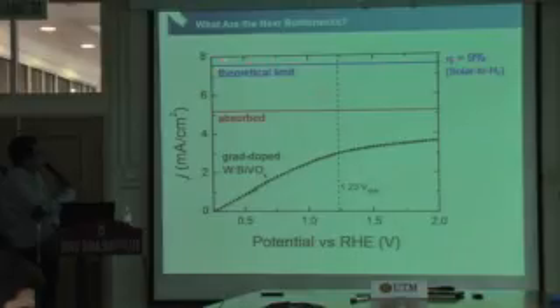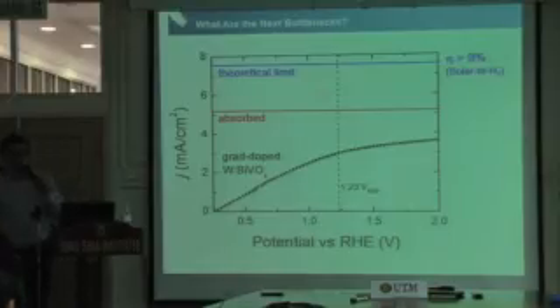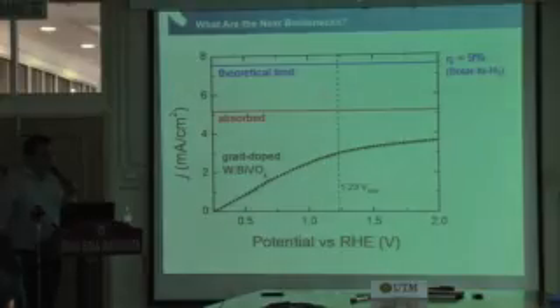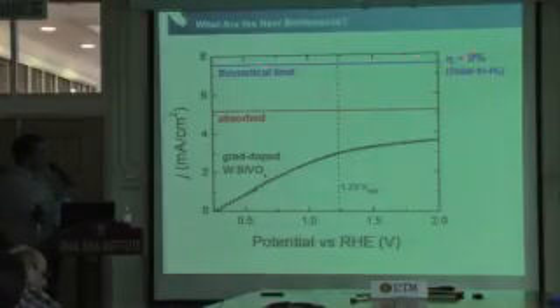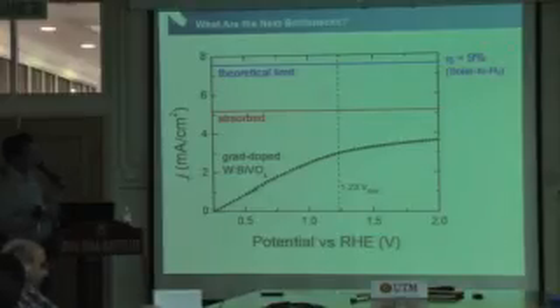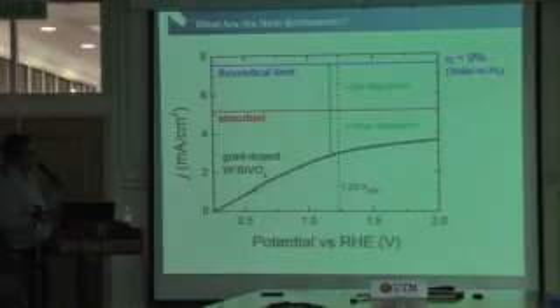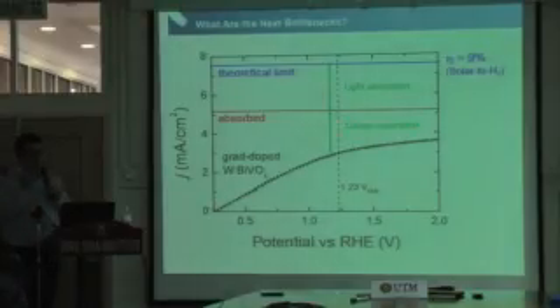And the blue line over here is the theoretical limit for bismuth vanadate, basically determined by the band gap. The band gap is 2.4 electron volts. So if you take all the photons in sunlight that have energy higher than 2.4 electron volts and you integrate them, you will get 7.5 milliamps per square centimeter, or equivalent to about 9% solar-to-hydrogen efficiency. So looking at this, the difference between the red line and the black curve is caused by non-unity charge separation. We have improved the charge separation, but it's not 100%, and it's reflected here.